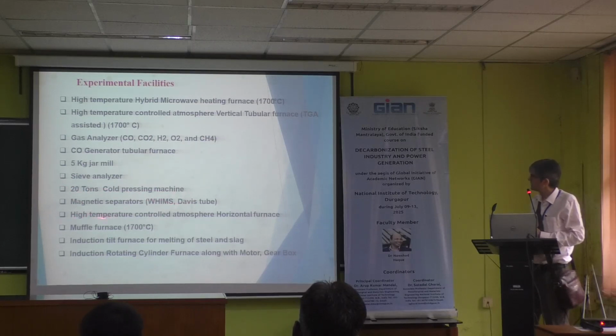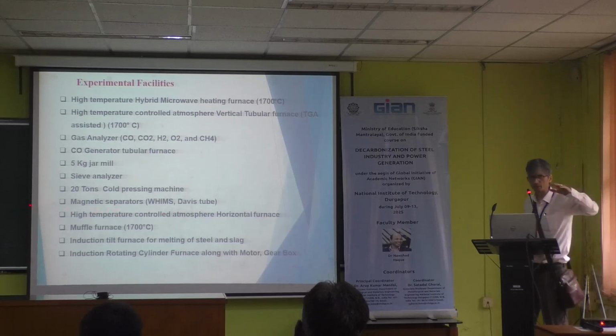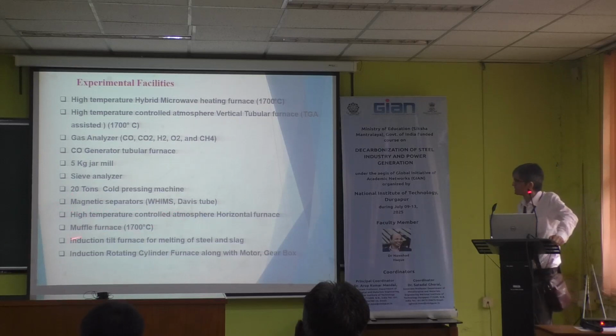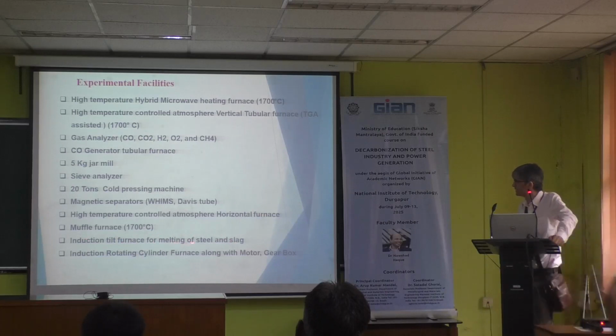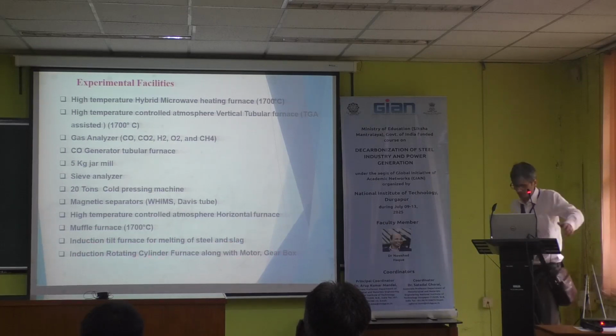We can also control the internal atmosphere of this furnace. For that it is connected to hydrogen, argon and CO2 cylinders, but the CO2 passes through the coke, so it emits CO. Then the muffle furnace. These are the two smelting facilities: an induction tilt furnace for melting of the steel and slag, and an induction rotating cylinder furnace. The last one is for doing dissolution studies. I will show you quickly.